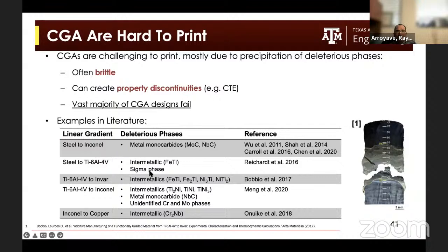There are many examples in the literature where people have tried to print linear gradients from all kinds of base alloys, from steel to Inconel, from steel to titanium 6-4, and so on. And it turns out that 90% of the time, these linear paths fail because you form brittle phases that end up compromising the mechanical integrity of the part. If you do a linear path, you could also create property discontinuities, for example in thermal expansion coefficient, that would compromise the mechanical performance of the part because you can generate internal stresses or other undesirable conditions inside the part.